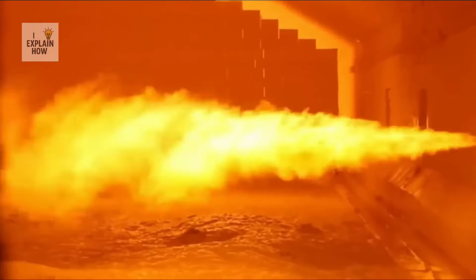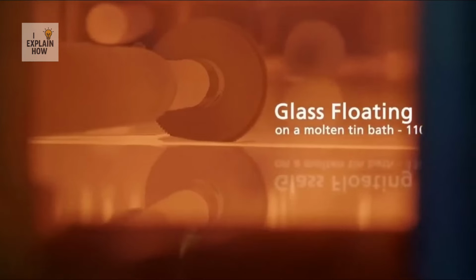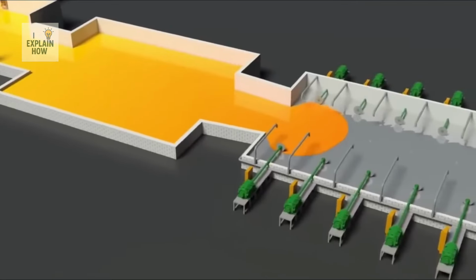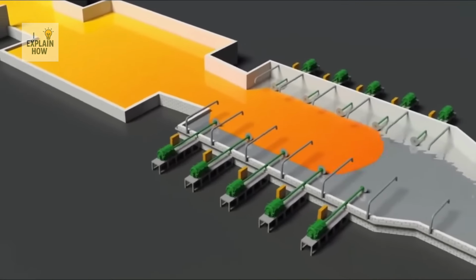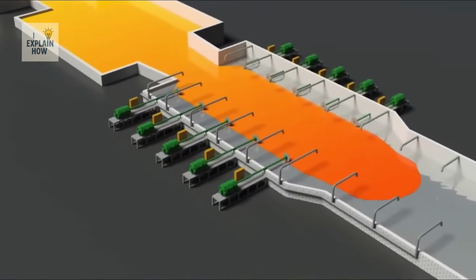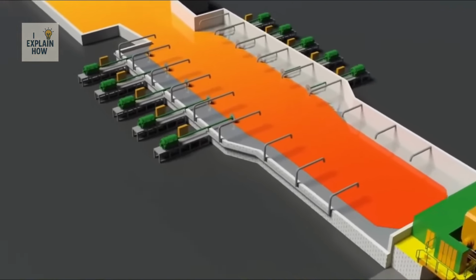The molten glass then passes into a hotter zone to remove bubbles and impurities, ensuring perfect composition and homogeneity. At around 1100 degrees Celsius, it flows gently onto a bath of molten tin in a protected atmosphere of nitrogen and hydrogen to prevent oxidation.